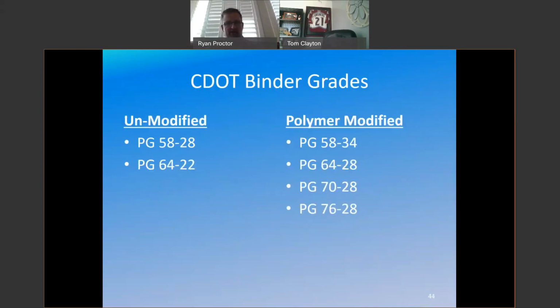So here are some CDOT binder grades. If you think about my rule of 92, you can see which ones are modified and which ones aren't. 58-28 and 64-22 are unmodified. They're used a lot in municipalities that aren't strictly for CDOT. They're cheaper. I'm not going to spend any time talking about costs, but you can imagine polymers add some significant cost to a binder. And then the polymer modifieds on the right, you might want to use a 58-34 in a colder climate. 76-28 might be your I-25 mix that you're looking for to resist rutting.